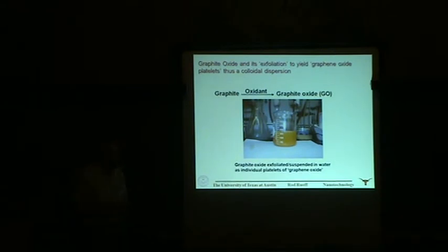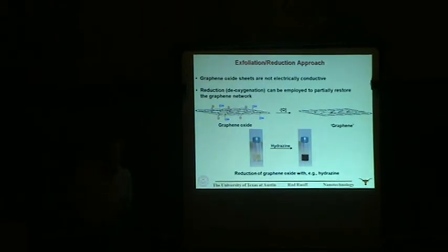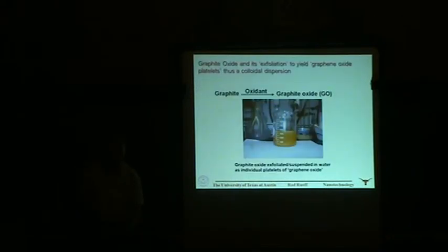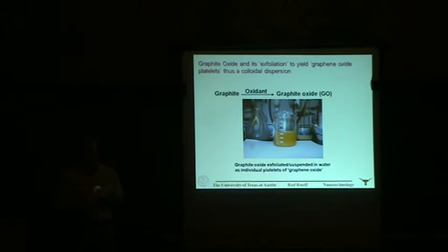So what is graphite oxide? It is also a layered material, and the chemistry of the individual layers is like this. So these chemical handles, like epoxide groups, hydroxyl groups, and carbonyl and carboxylic groups on the edges, mean that this material really is quite different than pristine graphite. So we start with graphite, and then we do chemistry where we wedge intercalants between the layers, and we hit it with a very strong oxidant like potassium permanganate, or potassium perchlorate, and that drives oxidation of the layers.